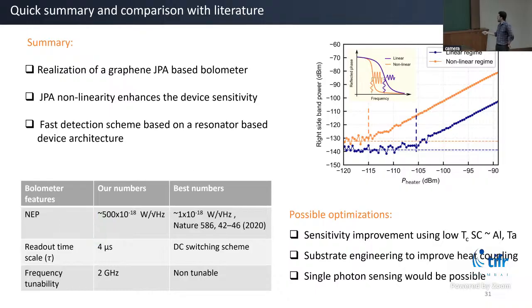One can be to choose a low Tc superconductor. The motivation there is to make weak Josephson junctions, because they will be more susceptible to external perturbation. So it can go normal very easily for a little bit of dumped heat. If you use a low Tc superconductor like aluminum or tantalum, that can improve the sensitivity.